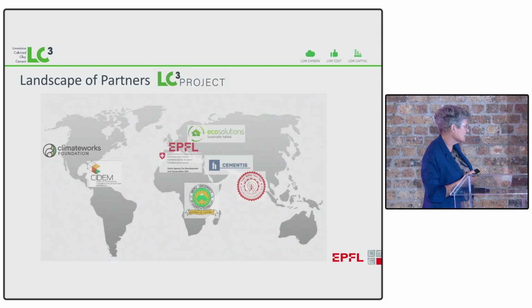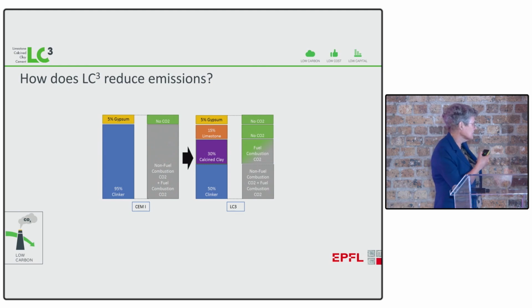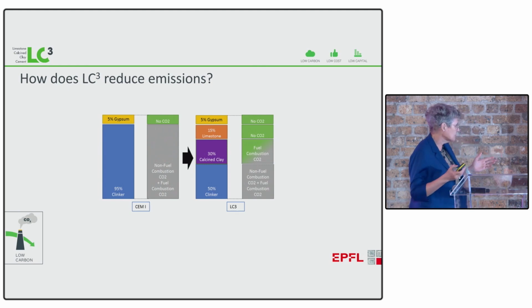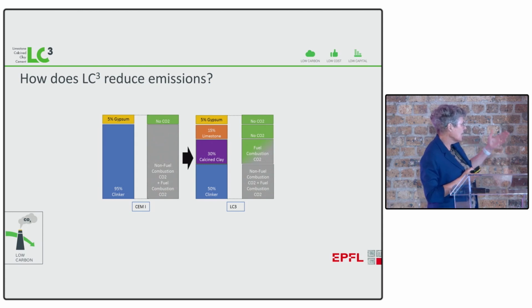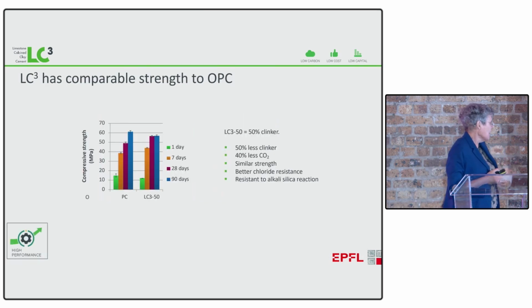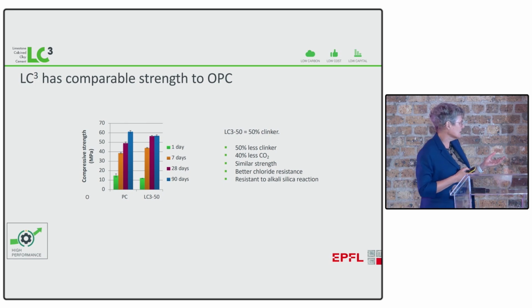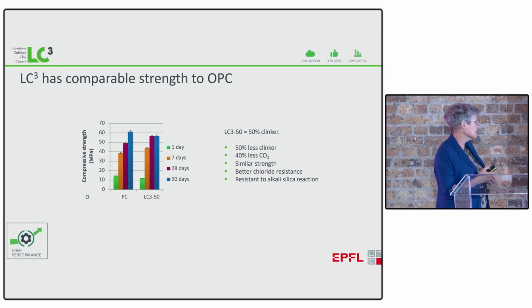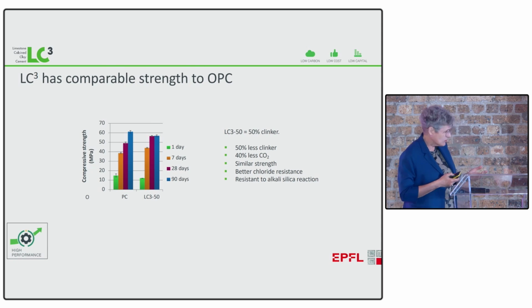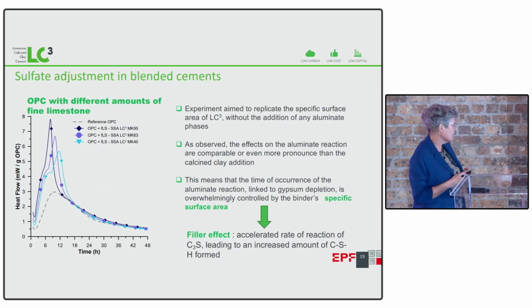We've developed it with a landscape of partners in Switzerland, India, now Kenya. And basically what we do is we take about half the clinker, but we can even substitute larger amounts now, and we replace half of that CO2-emitting clinker with this combination of calcined clay and limestone and gypsum. And I'm going to come back to the gypsum later because that's quite an important point. And then with this combination, which we call LC3-50, you can see we can get comparable strength to the reference Portland cement, and we can start to get that strength as early as 7 days, and even at 3 days, even at 1 day, the strength is nearly the same as the reference.